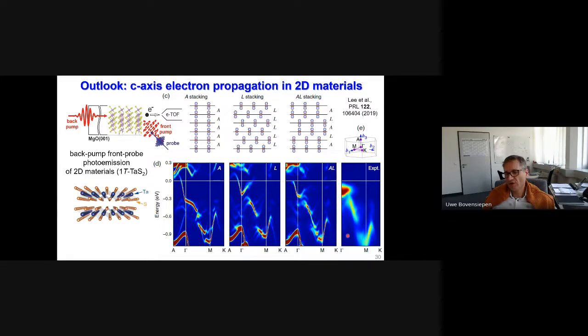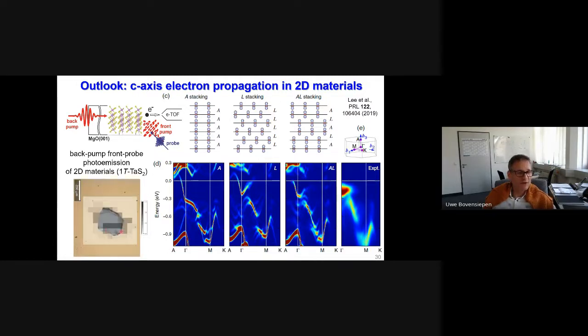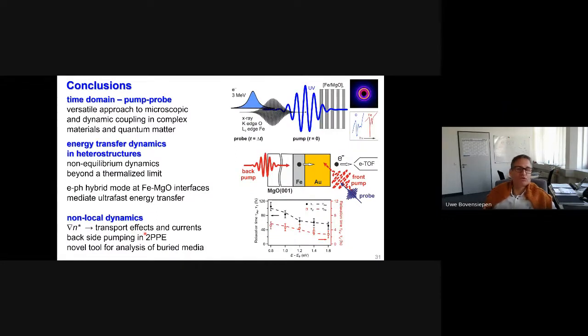And earlier ARPES studies could not contribute very much because they are not sensitive to these states above the Fermi level. So this is where we currently are. This is one of these tantalum disulfide crystallites, where with the laser pulse we can basically sit on or beside this crystallite, and this is also work in progress. So this brings me to the conclusion.